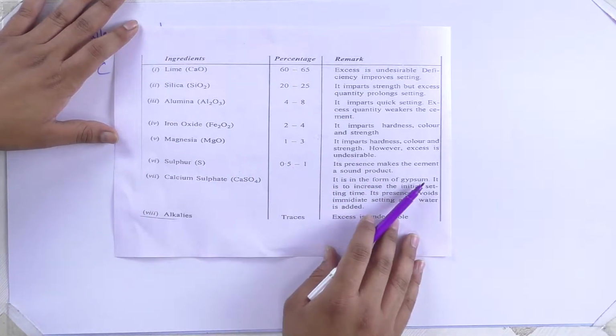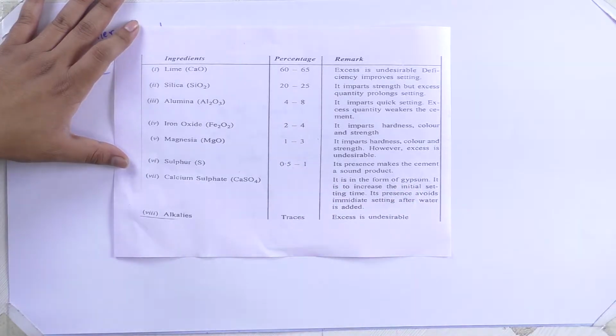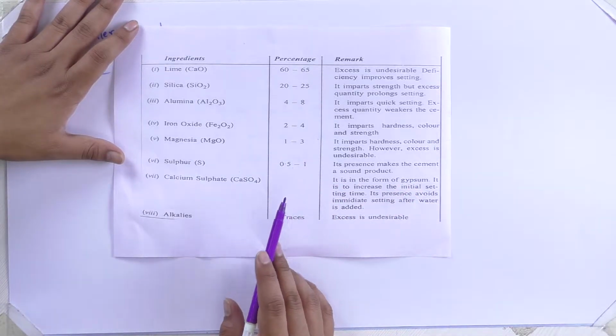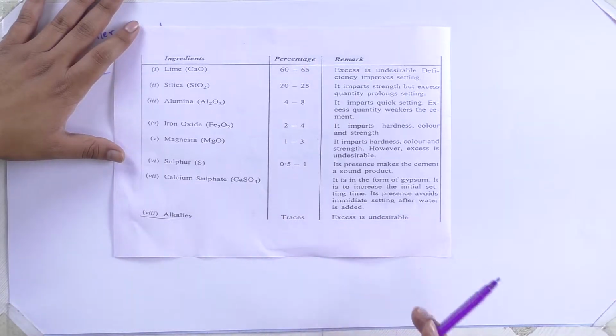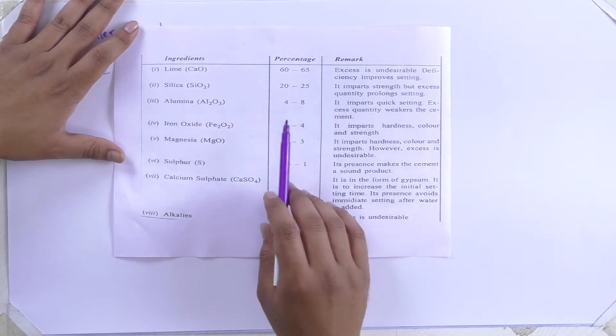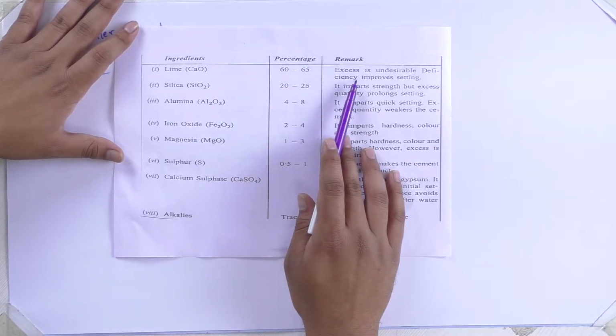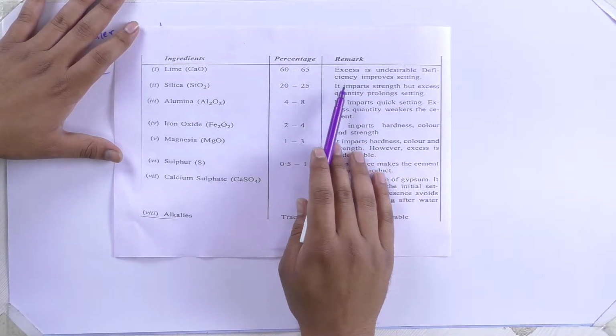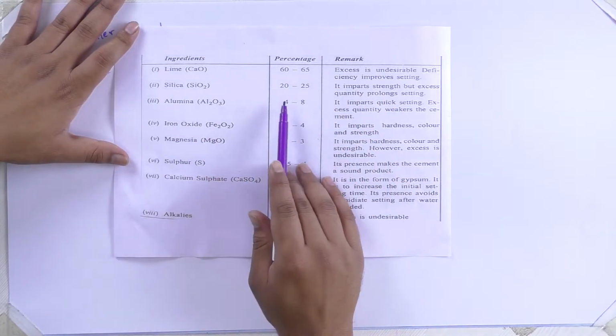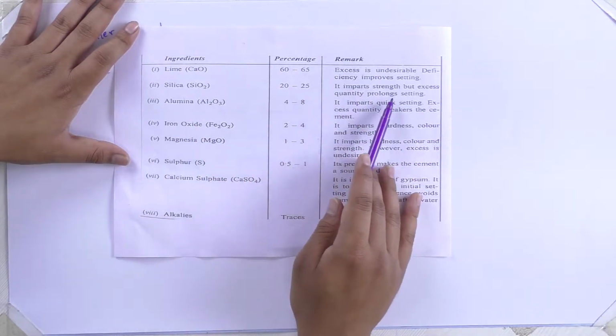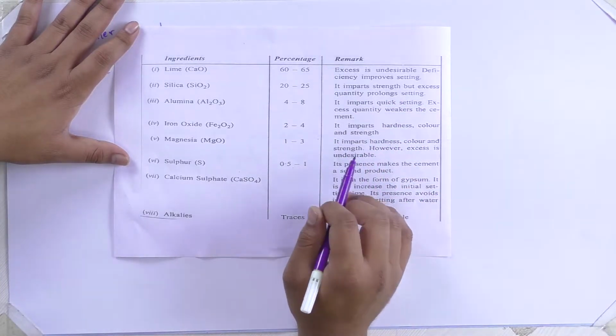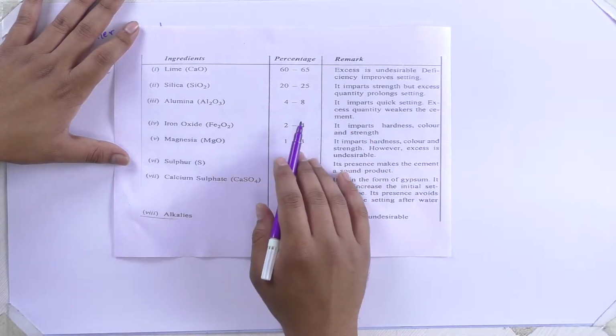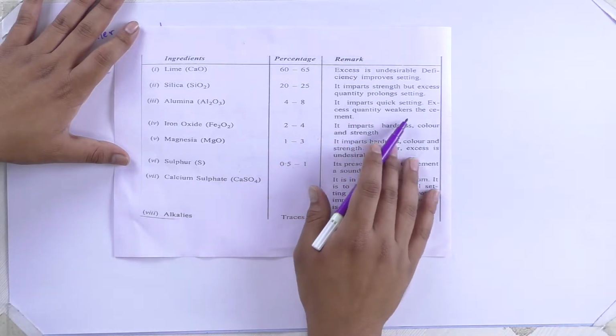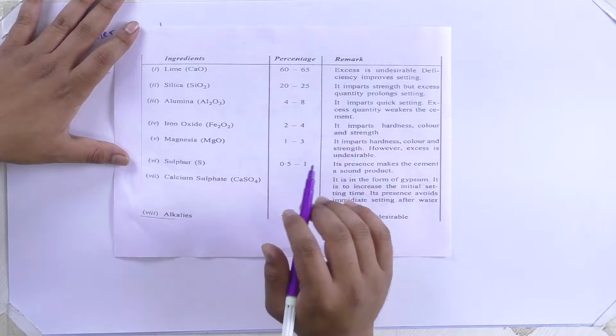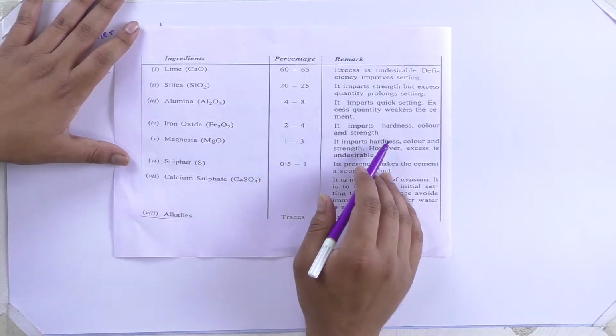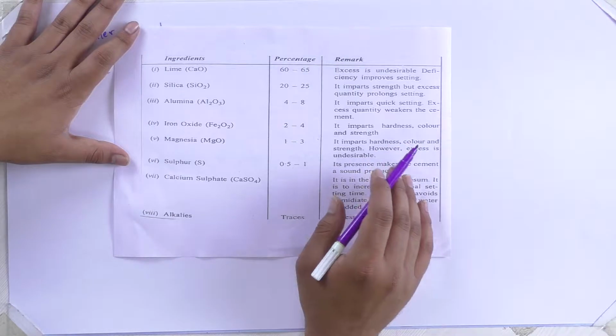and the percentage of each ingredient is given here, and also their nature of work in binding in the RCC is explained. Lime is in the percentage of 60 to 65, and excess is undesirable, deficiency improves setting. Silica, used in 20 to 25%, imparts strength, but excess quantity prolongs setting. Alumina in 4 to 8% imparts quick setting, and excess quantity weakens the cement. And iron oxide in 2 to 4% imparts hardness, color and strength.